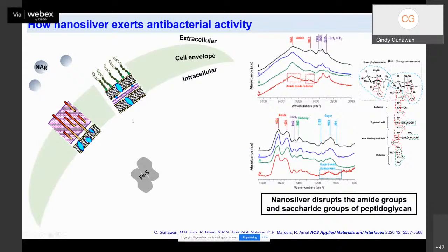So again, this is our bacteria. These are the cell envelopes of bacteria. This is the cell envelope of a gram-positive bacteria, and this is the cell envelope of a gram-negative bacteria. So how does nanosilver target the cell envelope? Silver nanoparticles, when exposed in aqueous medium, will leach soluble silver. And during this dissolution process, there could be a generation of reactive oxygen radicals, or ROS. And we have shown that this ROS can cause oxidative damage on the cell envelope.